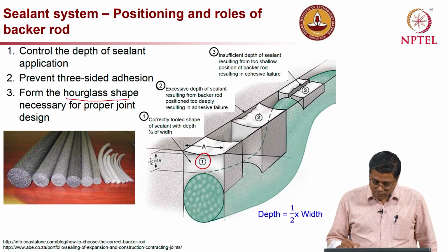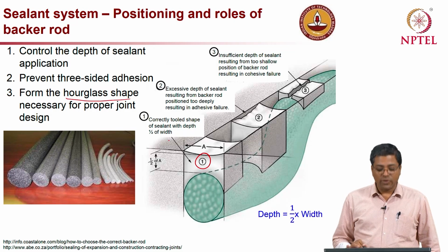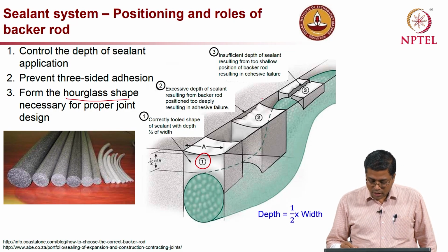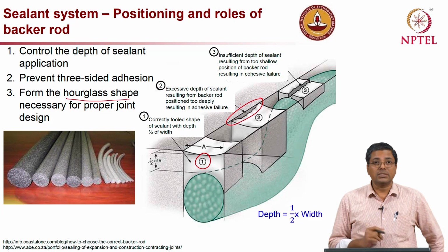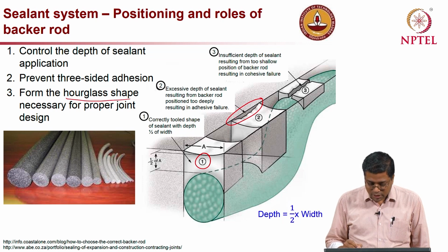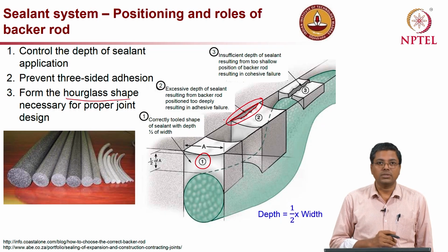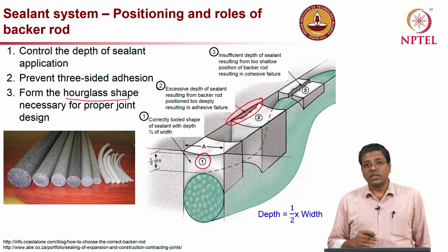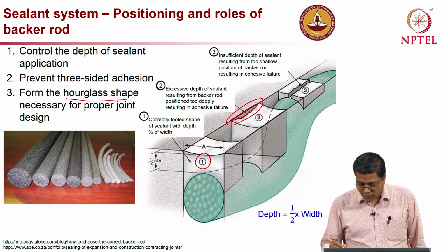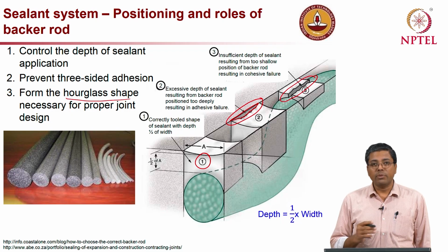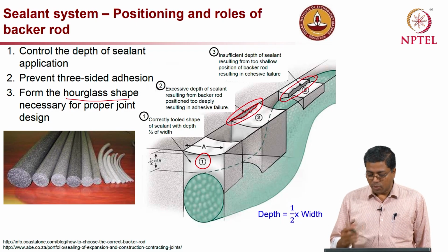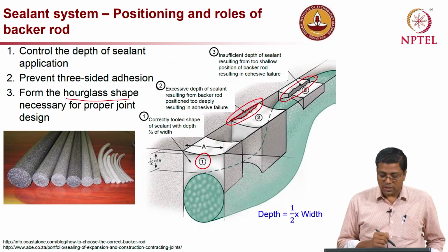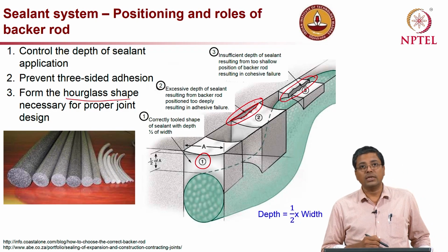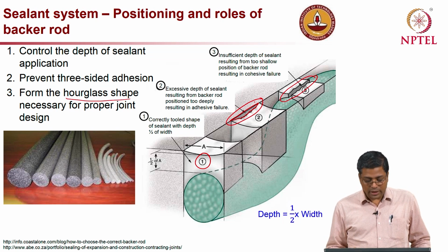So, what is the problem here? If you see case 1, everything is perfect, proper joint, no problem. In case 2, because you have more thickness, there will be a possibility of this elastomeric material getting detached from the edges or from the concrete surface, which is not good. Now, if the thickness is too little, the failure mode will be something like this. That means it is failing because of poor cohesion. In case 2, it is mainly the adhesive failure, in case 3 it is mainly the cohesive failure. I will discuss this in more detail later.